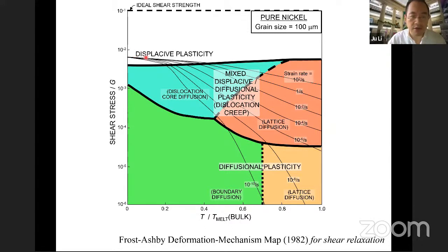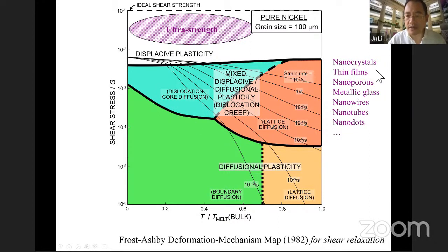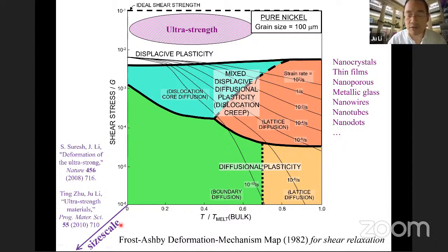So generally we see that conventional materials have inelastic relaxation, inelastic deformation, very far away from the ideal strength limit. However, with nanocrystals, thin films, metallic glass, nanowires, nanotubes, and nanodots, we now have a lot of materials with strengths at this level. Fundamentally, this is because this map was for conventional coarse-grained material with 100 micron grain size. All these deformation mechanism maps shift when we reduce the grain size, the thin film thickness, or the sample size. That is the intrinsic reason: we modify the defect population dynamics, which enables very high strength.